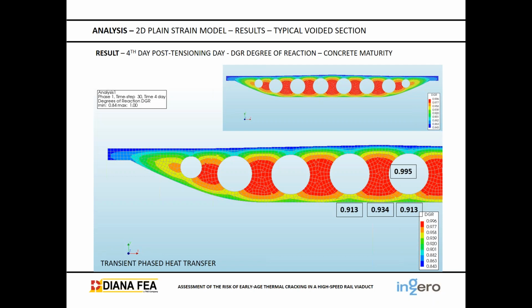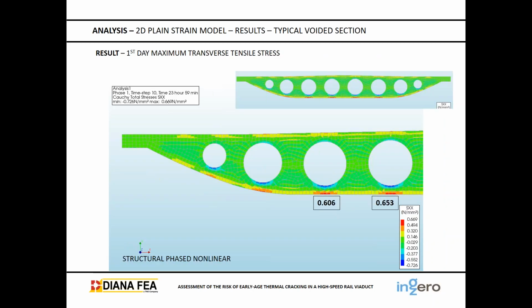On the fourth day, we go on to the degree of reaction, which indicates the maturity of the concrete. So we see that in the inner part, it's nearly one. Meanwhile, in the outer part it's 0.93, and below the voids where the cracks have been placed, it's 0.9. It's less maturity than in the inner part. Okay.